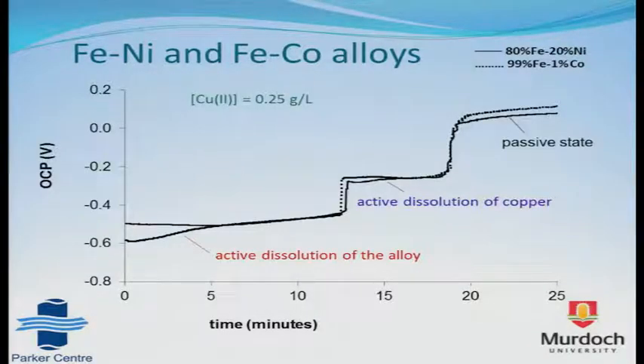Similarly, you see the same behaviour with iron nickel and iron copper alloys, iron cobalt alloys, which represent what we may find in the reduced ore. And you have this initial active dissolution followed by no longer dissolution of iron, and then the dissolution of copper, which is intermediate. Once the copper is all dissolved, the iron is passive, and any nickel and cobalt present in the alloy is not going to be recovered.